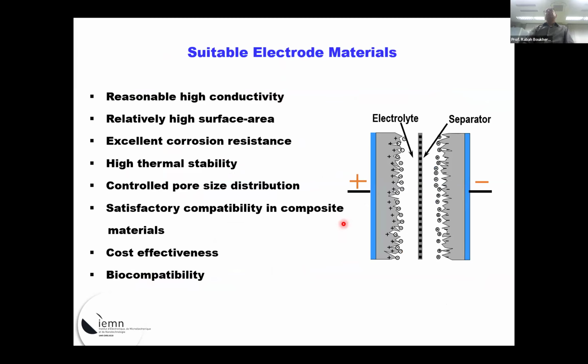So what are the suitable electrode materials? Certainly, the ideal material is almost impossible to find because, especially with a supercapacitor, you have a porous material, so the conductivity is decreasing. You need something with reasonably high conductivity, relatively high surface area to store as many charges as possible, and something that resists corrosion, especially when you work in electrolytes. More specifically, in alkaline or acidic conditions, some oxides are not stable in acid, for instance, but you can also induce oxidation even of carbon materials in alkaline or acidic electrolytes. You would also expect high thermal stability, so they can run over a wide range of temperatures.